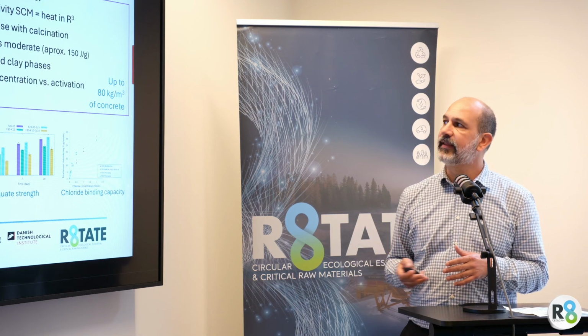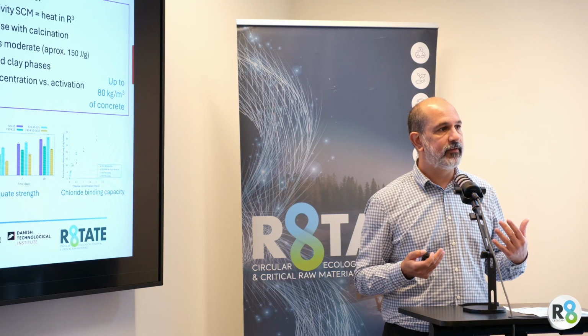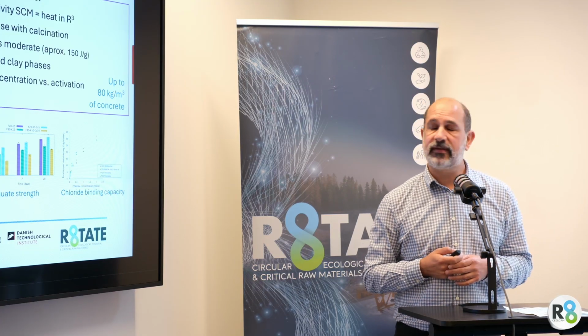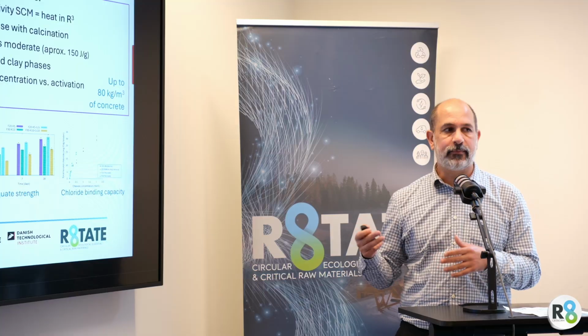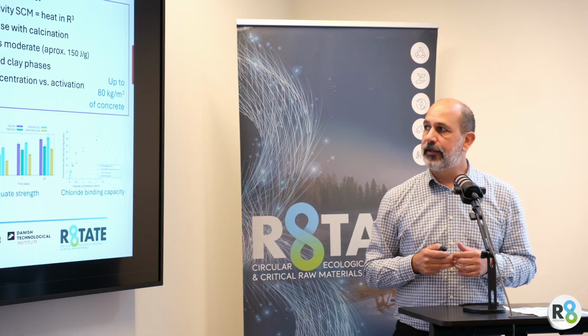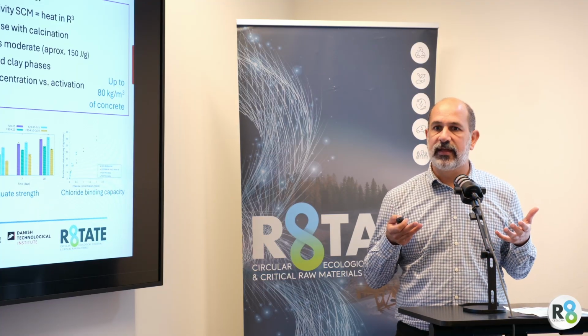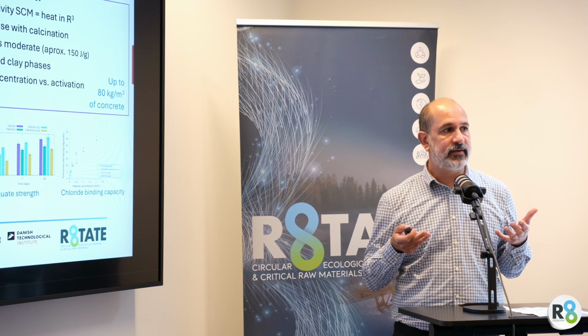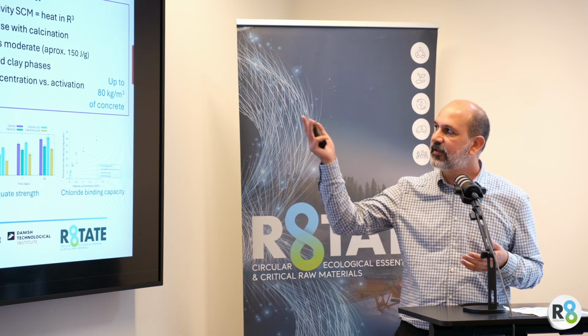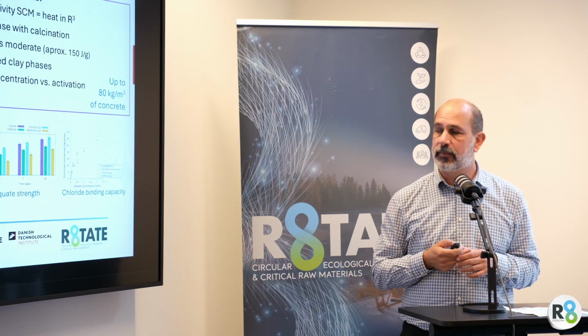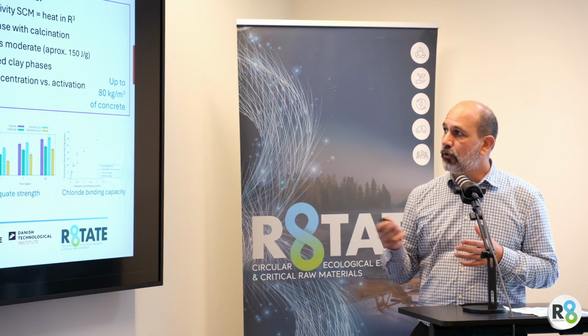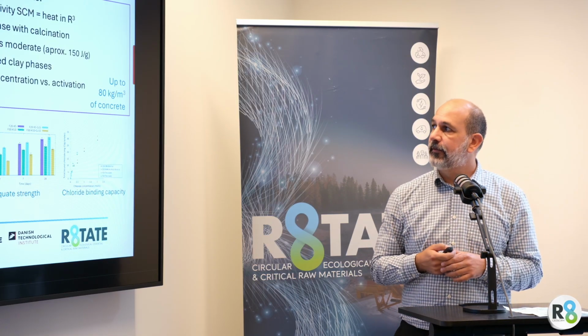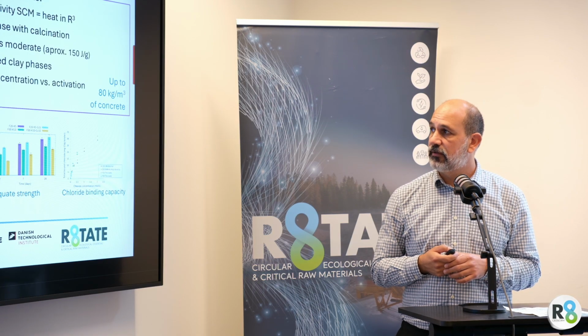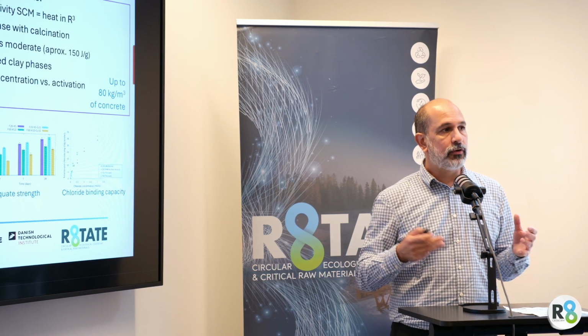Again, the content of clays was somehow limiting the performance of the material. In this case, because it was too low, we would like to have a higher content of clay in the material so we could reach even higher reactivity than 150 joules per gram. So there's still some possibility of continuing the research by concentrating these clays.